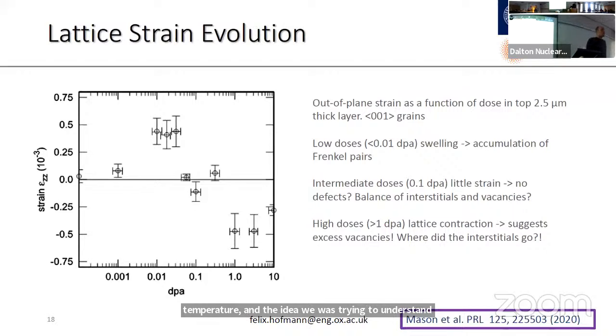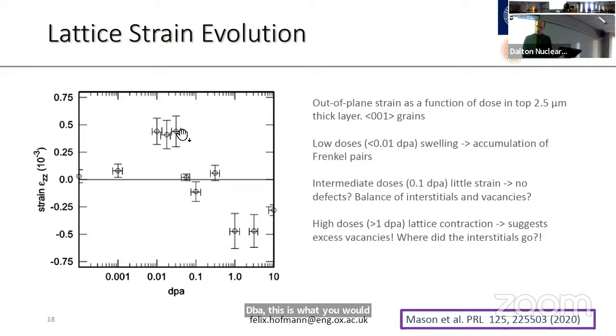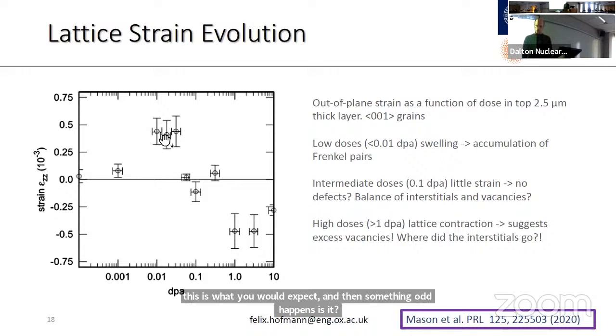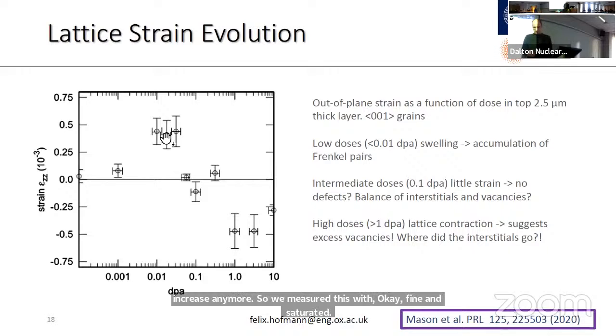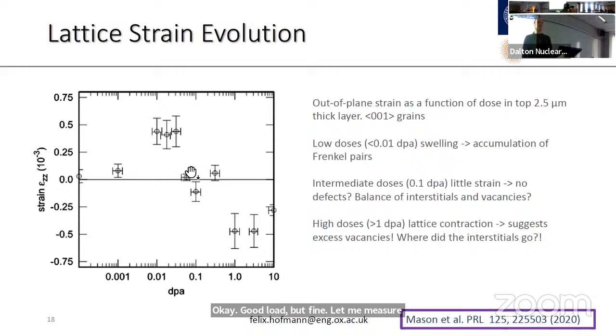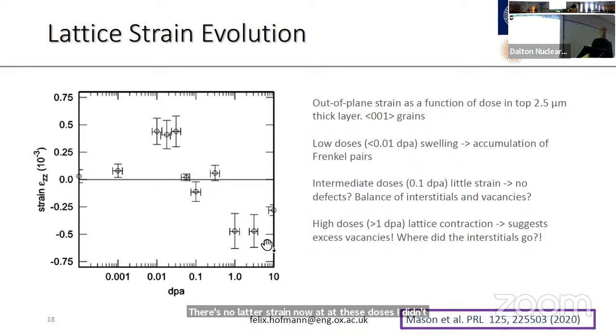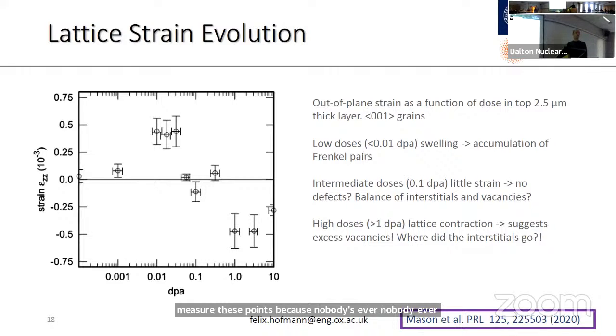First thing we did again was to measure lattice strains, and we saw something really very strange. Here I'm showing the lattice strain, or out-of-plane swelling, as a function of dpa. Initially, fine, your lattice strain increases with increasing dpa. This is what you would expect. And then something odd happens: it doesn't increase anymore. We thought, okay, fine, it's saturated, a bit low, but fine. Then we measured these points, and we were like, hang on. There's no lattice strain now at these doses. And then we measured these points, and we thought, hang on, something's clearly wrong, because nobody ever reports that the lattice actually contracts when you irradiate, right?